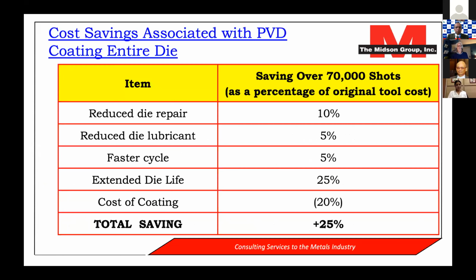So the caster actually did a quantitative comparison and looked at these 4 or 5 different parameters. And they looked at the savings after 70,000 shots as a percentage of the original tool cost. Reducing die repairs, they said that represents a saving of 10% of the original tool cost. Reduced die lubricant, a saving of 5% of the original tool cost. Faster cycle, 5% saving of the original tool cost. And extending die life is a big one. Obviously, that's a huge one in terms of cost savings.